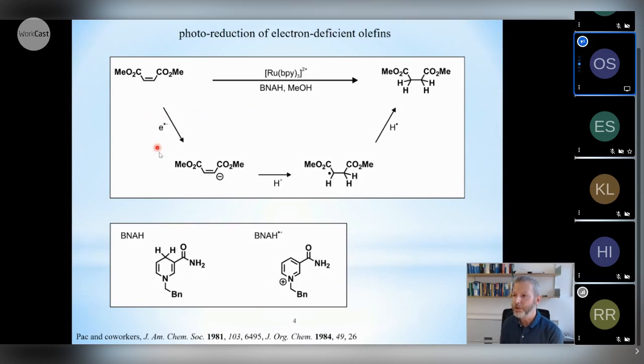There's a first reaction step here leading to this radical anion, and that is possible because the starting material has these very electron-withdrawing substituents. And that activates it, of course, for single electron transfer. Subsequently, there can be protonation of this radical anion, and the proton source is the oxidized form of the sacrificial electron donor, leading to this intermediate here, which, following uptake of a second equivalent, formally of hydrogen atoms, can form the ultimate product.